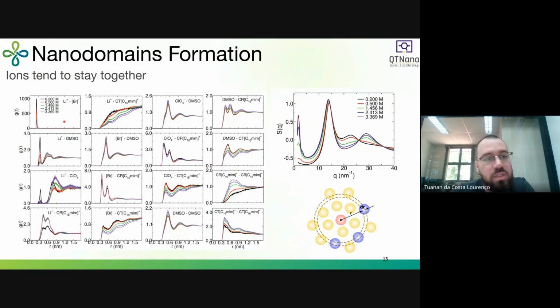However, when we increase the concentration of ionic liquid, we see a decrease of this first peak. If you look here at pink, there is no peak here, and we have an increase in the second peak. That means that those DMSOs that were around the lithium now are not around the lithium anymore. They are in the second solvation shell because something is inside the first solvation shell.